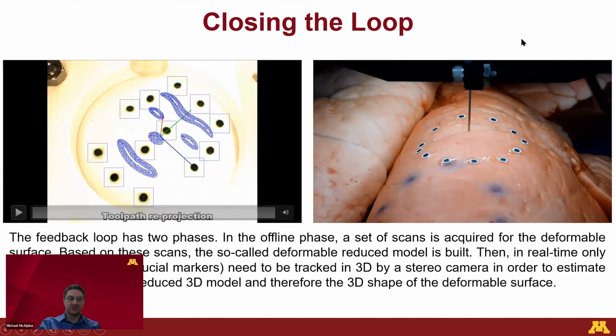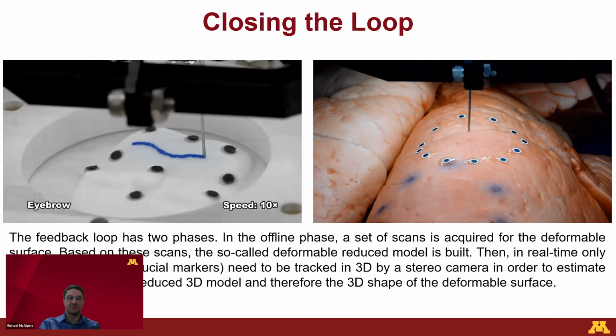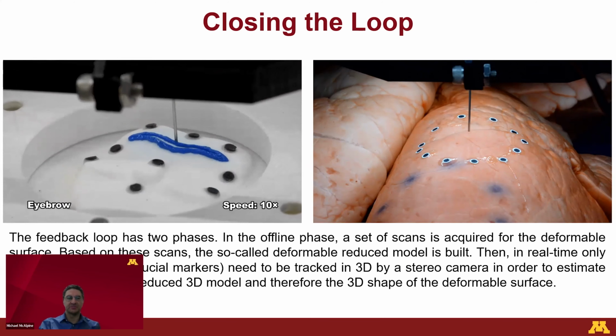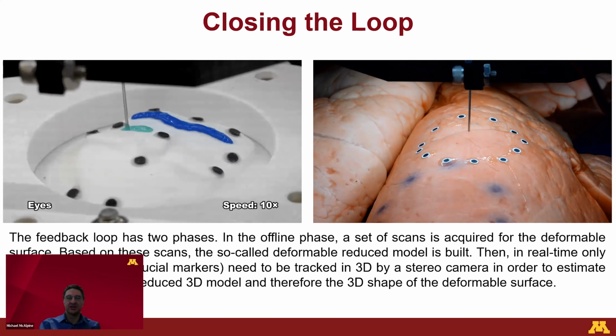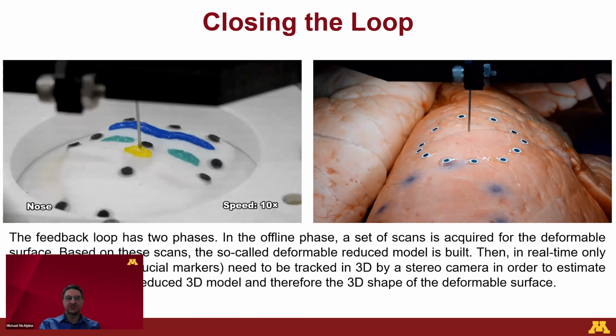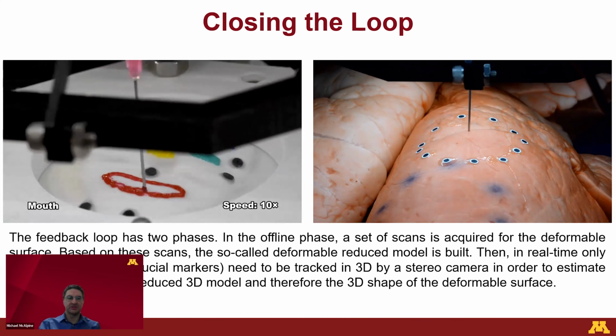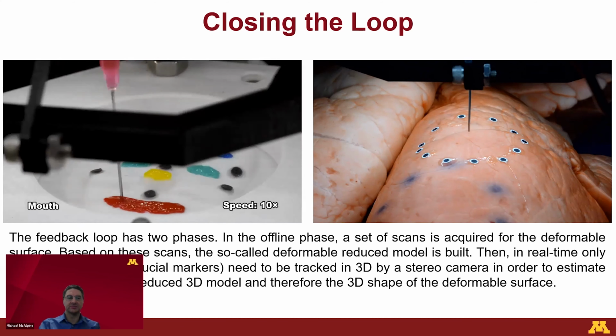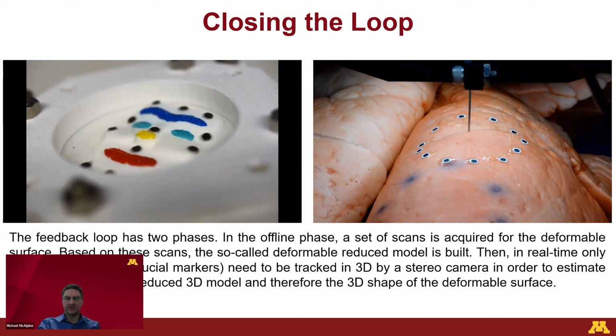Okay, so the trick here is that we separate this into two phases. We do a set of pre-scans beforehand to reduce the complexity of the problem and build a reduced model, so that we'd only need a few tracking markers in real time to track the deformation. Once we figured that out, first we started with a membrane that we pump air through. So the membrane is expanding and contracting. You can see the printer is moving up and down as it tracks that motion and is able to fill in the membrane with this smiley face based on various colored silicone inks that you see there.